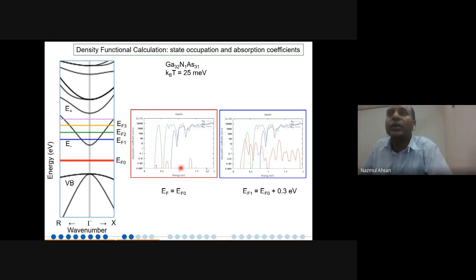And I'm talking about that I'm playing with the Fermi level, or technically I'm playing with the absorption coefficient with the band gap. By playing with the Fermi level, if you dope more and more, then you can shift your Fermi level and you can play with the absorption coefficient of your material.